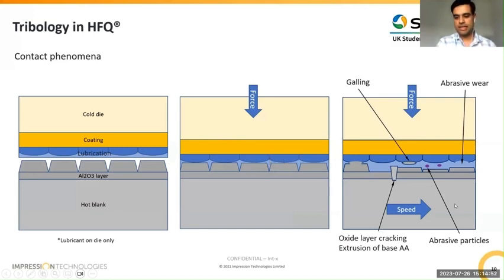And then when there's sliding action, when the part wants to form, then there are a lot of things happening at the same time. There is breaking of the brittle aluminum oxide layer, which can lead to extrusion of base or softer aluminium alloy, which then can come in contact with the tool steel or the tool surface and get, I won't say cold welded, but get, let's say, chemically or mechanically adhered, which is galling. And then there are some broken off abrasive particles of aluminium oxide or of the tool surface as well, because aluminium oxide is the second hardest material. So it can also wear and remove particles off the tooling surface.